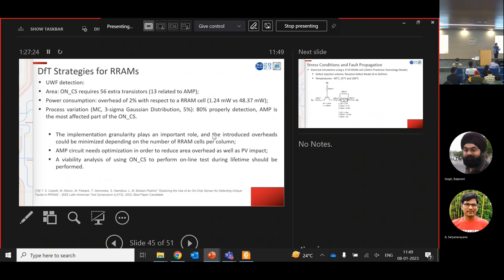Okay, so you know what the maximum of reset and set operations that you can perform is. So you are going to have a threshold for that. And when your device is aged, you are going to reach this limit of reset operations, for example, that is 7 for this specific memory, and you are not going to really put the device in the high resistance state. And so the idea is how you can monitor this degradation. Okay, for NXP, this is really critical because they wanted to understand how to monitor the degradation to understand how reliable the device is.